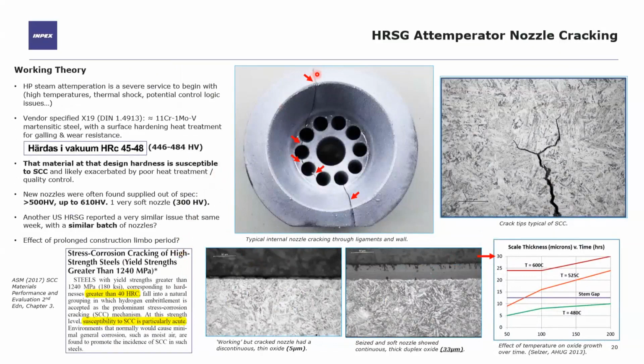Internally, this is what many of the cracked nozzles look like. It appears that cracking has started at one or more of the ligaments. The stresses have then allowed a crack to initiate and propagate in the next ligament. And before you know it, you're at the wall and making your way through the wall.